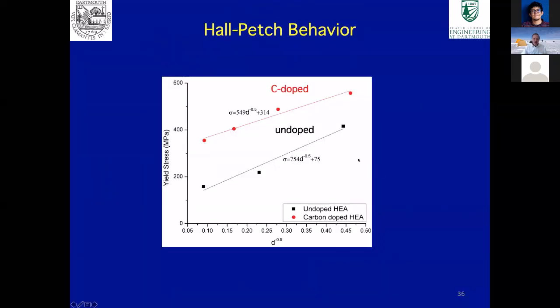If you look at the Hall-Petch behavior, then you can see this linear relationship with the carbon doped material and undoped, and they look like they have different slopes. But you have to remember that when you're looking at these points, the difference between them isn't simply the difference in grain size, but also is changing the precipitates in the material. And as we're forming carbides in the material, we're taking carbon out of solution.